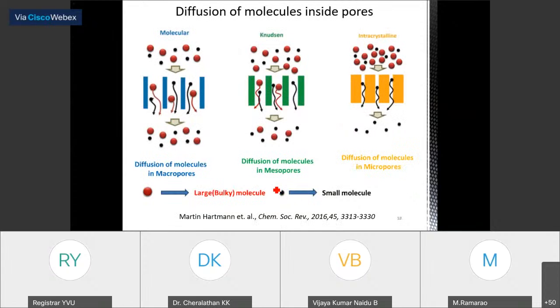So when we talk about diffusion, in the case of zeolites, intracrystalline diffusion is taking place in the micropores. So it limits the bulky, larger molecules which have a size bigger than the micropores. They cannot enter into the pores. Also, the smaller molecules, when they enter into the pores, have some kind of restriction to diffuse through the pores. But in the case of larger pores like macropores and mesopores, both bulky and smaller molecules easily diffuse into the material.